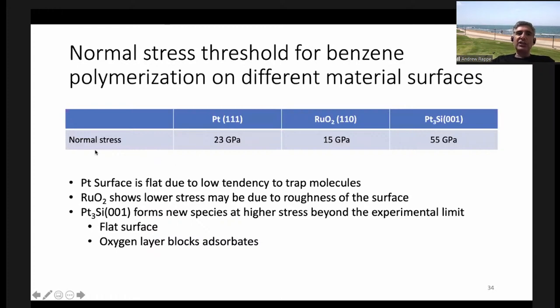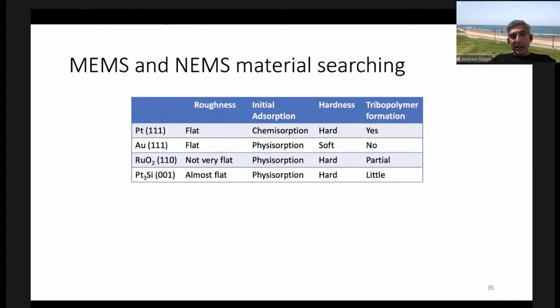But our comparison, just to summarize what you've seen, is that the normal stress to make a reaction is 23 GPa for platinum, 15 for ruthenium dioxide, and 55 for platinum-three silicide. So this analysis allows us to understand the chemical reactions that are involved under stress. We would say tribochemistry or mechanochemistry. And then we can do materials design and rate different materials.